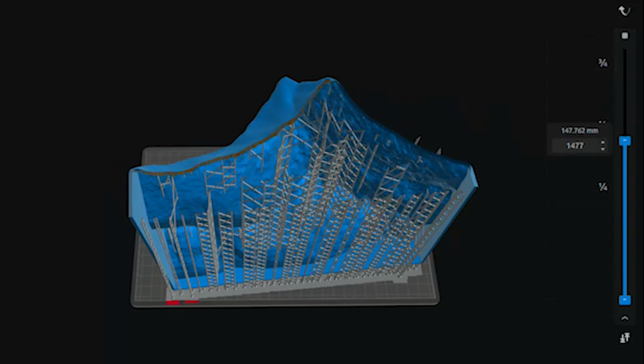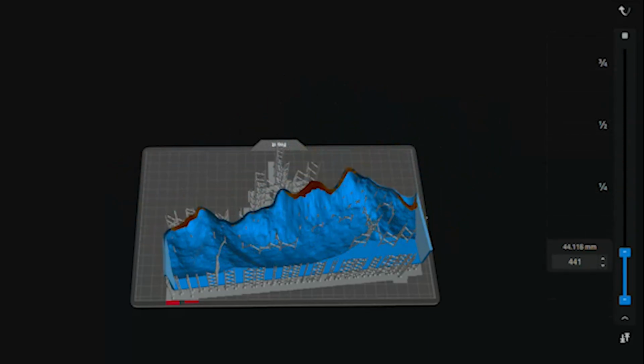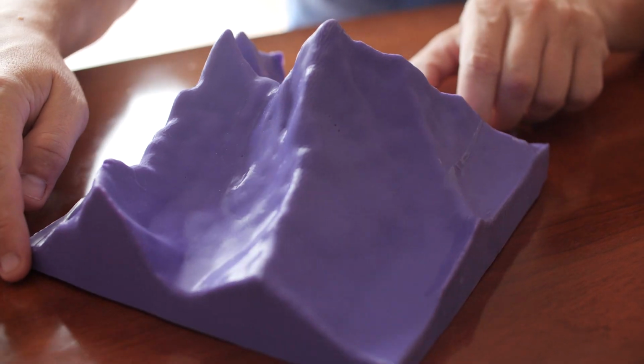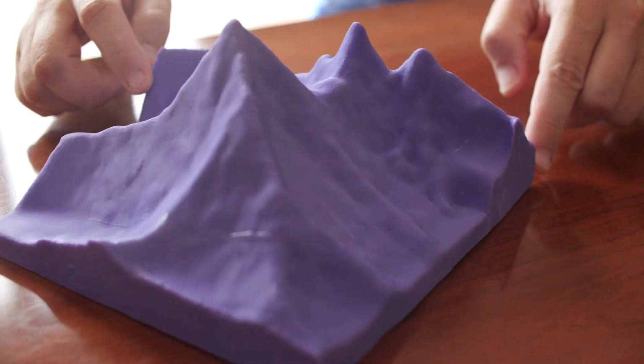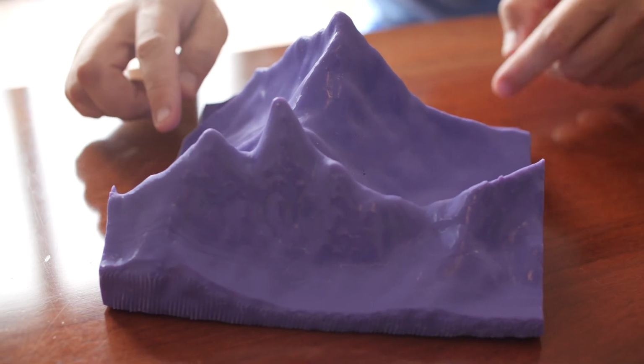Once we had our 3D model of Mount Everest, we used it to print a plastic mold with approximately 2 mm thick walls. The print took around 6 hours, which was double the 3-hour estimate from the software, using 0.1 mm layers. Unfortunately, the result was not ideal: striped, slightly warped, and far from perfect, likely due to a lack of support elements.